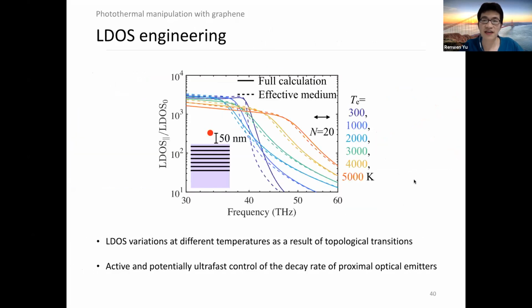And as a result of this topological transition, we can see that when we increase the graphene temperature, for example, again at the frequency of 42 terahertz, we can have an enhancement of the local density of states. It's about three orders of magnitude enhancement of local density of states when we increase the temperature due to the topological transition by heating graphene.